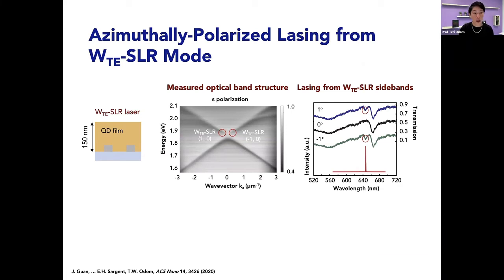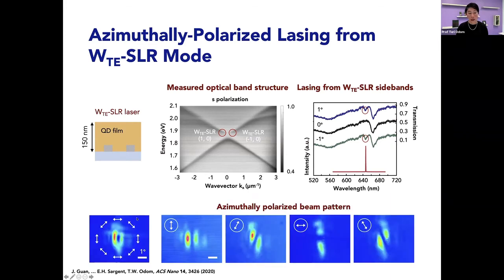We can also change the thickness. So in this case, we reduced the thickness of the quantum dot film. So instead of coupling to the waveguide TM SLR mode, we're coupling to the waveguide TE SLR mode. And so that's what happens here. And then we also get this nice narrow emission. And different from the TM SLR mode, we now have azimuthally polarized beams. And so we are able to achieve either radially polarized or azimuthally polarized lasing simply by changing the quantum dot film thickness. And that relies on what is providing the feedback, where the energy of the emission of the quantum dot intersects these modes used for lasing.